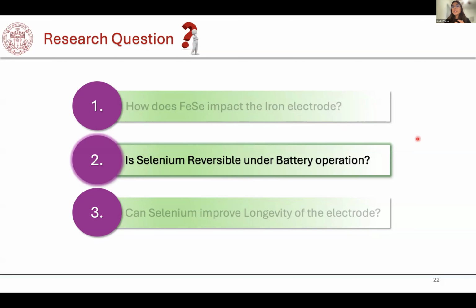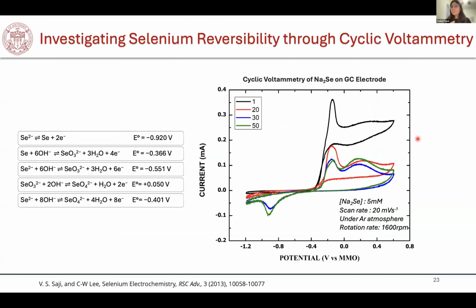I wanted to see how selenium would behave in that potential window, and for that we do a very simple electrochemical analysis, which is cyclic voltammetry. From this cyclic voltammetry analysis of sodium selenide, I found that by the 30th cycle, as you can see, the CV becomes quite stable with well-defined oxidation and reduction peaks. This indicates that selenium is extremely reversible under battery operating conditions, which also adds up to our hypothesis of it being electrochemically reversible.